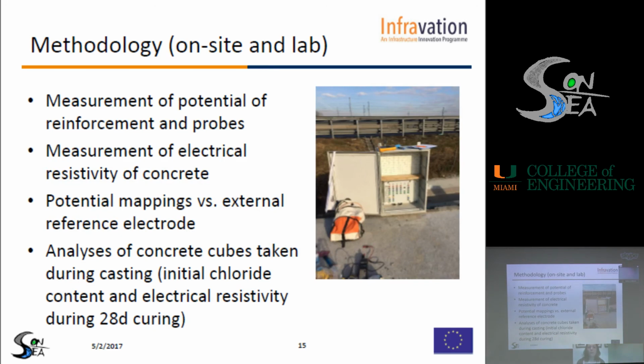Now I will describe the methodology that we have used so far, both on site and in the lab, in order to monitor the corrosion conditions of the reinforcement. Well, first of all, we regularly measured the potential of the reinforcement and the electrical resistivity of the concrete. So far, these measurements were done manually because the data acquisition system that we had planned to use is not ready yet. So we performed these measurements manually more or less once a month in the last 5 months of service.